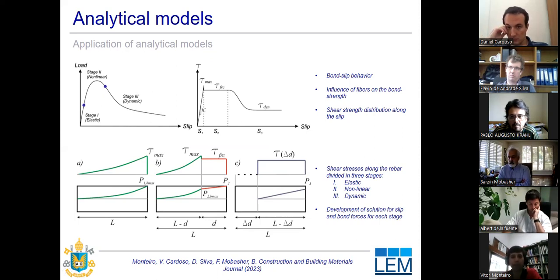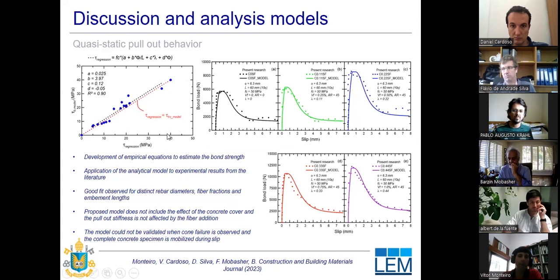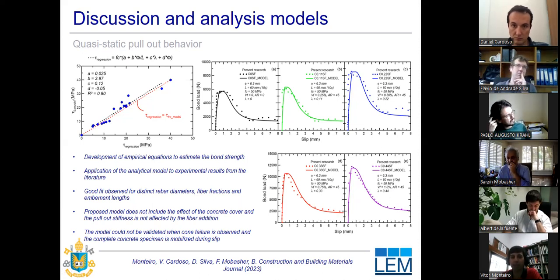the concrete matrix. So after we apply those shear stresses for different slip values, we can calculate the bond force in the interface and then obtain the load slip curve, which is presented here in this figure. So we applied the model for different results in the literature and also from the experimental results carried out in this research. We could observe a very good fit. So the use of the proposed three stages for the pullout presented a very good fit with the experimental results.